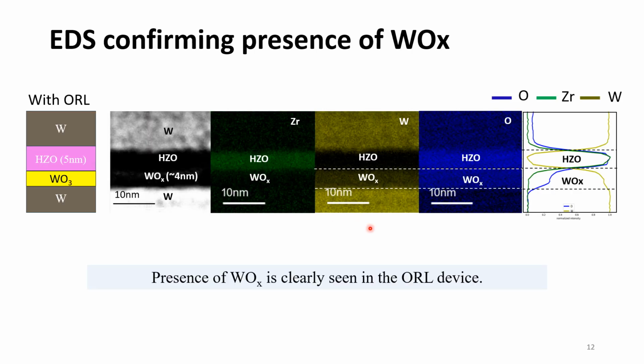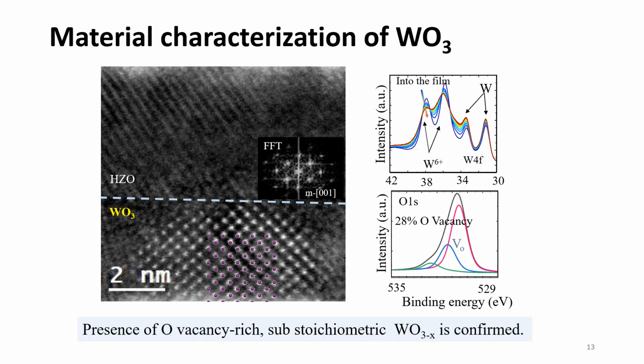We further did EDS scan on this ORL device. And from the material count coming from the tungsten and oxygen here, you can see that one tungsten oxide layer is actually getting formed at the bottom interface. And this is clear from the line scan on the right as well. Next, we did material characterization of this layer to find the stoichiometry of the tungsten oxide. So with the help of TEM imaging, we could see that this tungsten oxide is monoclinic in phase. And we performed XPS on this tungsten oxide layer and found that this is actually WO3 with 28% of oxygen vacancy, meaning this is a substoichiometric tungsten oxide layer.